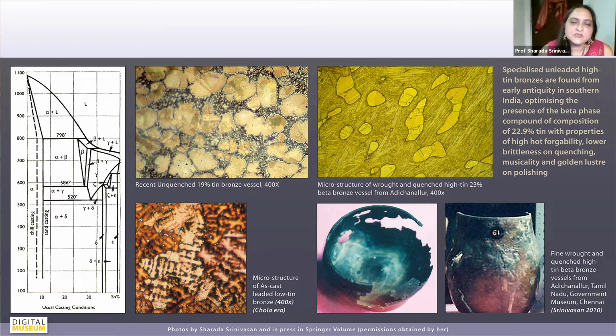And that quenching was very important because if they didn't do that, and if it slow cooled, then you get the formation of a very embrittling alpha plus delta eutectoid phase. And so they were really trying to aim for that quenched beta composition. And so you're looking at a microstructure of this bronze vessel from Adichanallur, and you can see these long elongated needles of martensitic beta phase. So that's how you can tell that this is a wrought quenched beta bronze. And in fact, it's a very spectacular formation of martensite there.